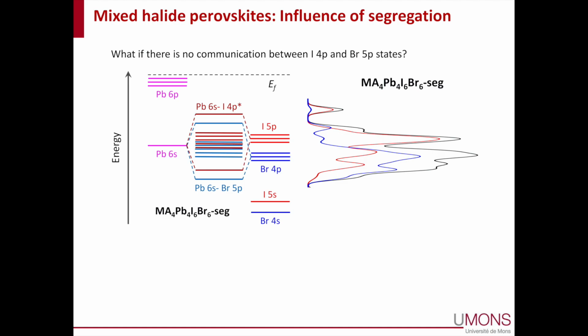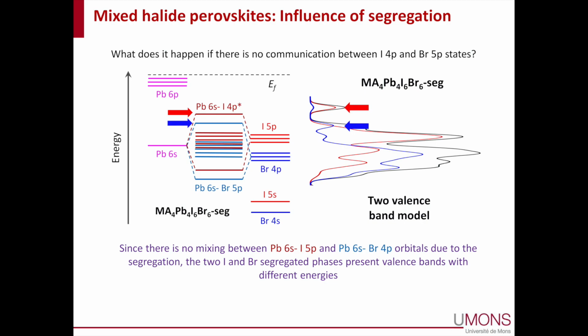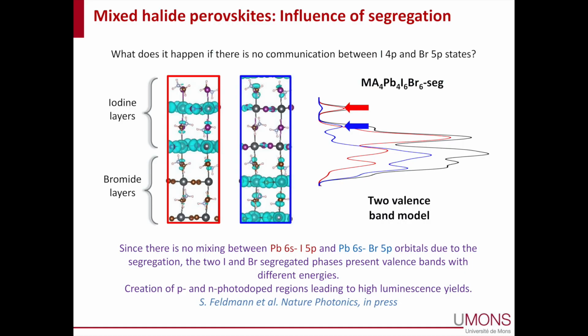Well, that's a rather easy case, because what happens simply is that you end up with a two valence band model, one associated with the hybridization with the lead and the iodine at higher energy, and a deeper band that corresponds to hybridization with the bromine, in blue here. And if you look spatially at the wave function, that's exactly what you find. So here we have the bromine layer, here the iodine layer. You can see for these two valence bands that they are either confined completely on the bromine or mostly confined on the iodine part.